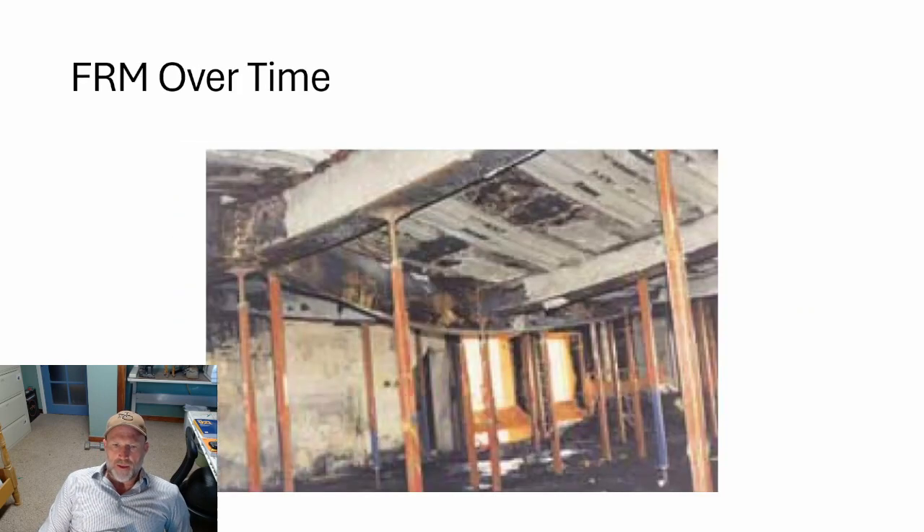There's one other factor: the smiley face effect at column 79. Once the fire transferred its energy into the beam, the smiley face profile formed. Then, as the traveling fire moved to other floors and left that vicinity, you effectively had a shorter beam due to that smiley face profile, and then retraction of the beam or girder. That retraction had a larger delta in thermal expansion — due to the new deformed profile — than the original expansion. This is most likely what caused the girder to be removed from the support of column 79.